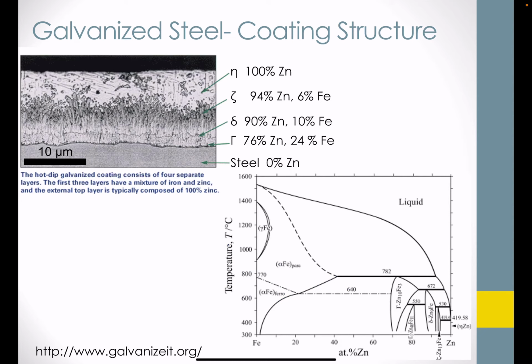When we consider what those composition bits of information of these coatings mean, we often turn to a phase diagram, which you may have seen in prerequisites for this course. So here's the phase diagram for iron zinc, showing a temperature y-axis. And so if you recall, we said that we typically apply zinc to metal structures like steel at about 450 degrees C, so that's about here. And we would expect that by walking laterally here in this territory, we'd eventually see the phases of the zinc iron system that may be present at the surface of these metals based on iron.